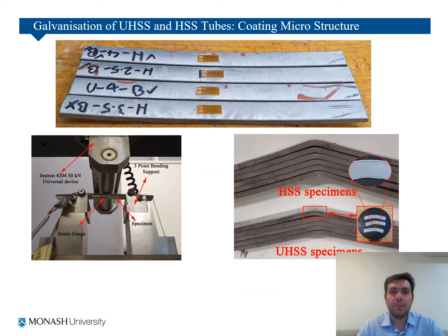Then we conducted some bending tests on these beam shape specimens to a certain strain. So the strain was measured for all of them and did not go beyond that. Then we cut the bent region and the intact region for micrographic studies.